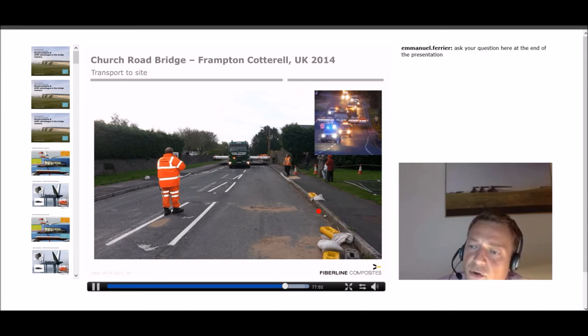For the connection of the parapet, they have to grout polymer concrete in, so you cannot use normal concrete. Because the alkalinity value is more than 10, it doesn't go down over 15, it stays always at the same pH value. It's more than 10, and isophthalic polyester is not alkali resistant.